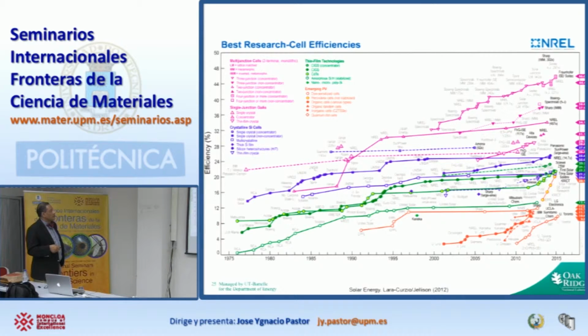And obviously, they show some very good behavior in these cases, but again, they are very, very expensive. You have these multi-crystalline systems, which are not as efficient as the single crystals, but they are less expensive. You have thick silicon films, and you can see the trend for silicon. So in the case of silicon, you are not going to exceed 30%. That's a theoretical limit for the efficiency of silicon-based cells, about 30%, okay? That's the best you're going to do with silicon, 30%.